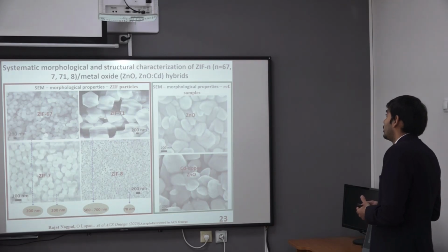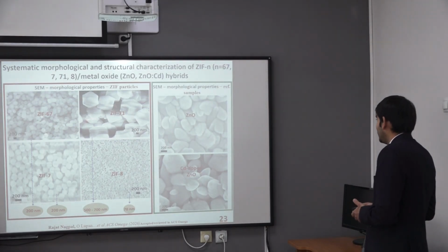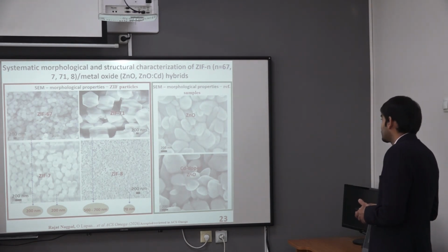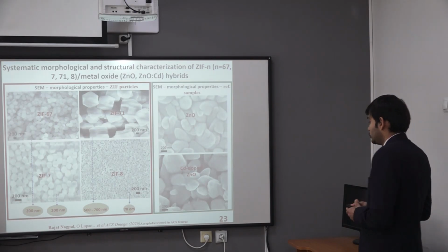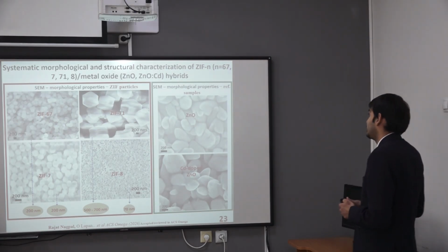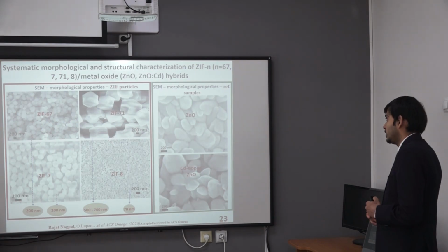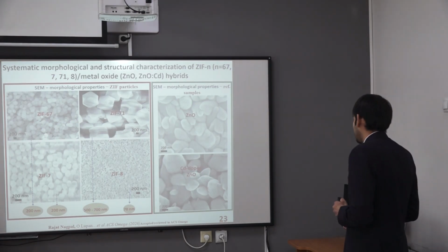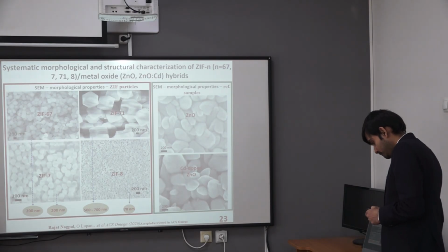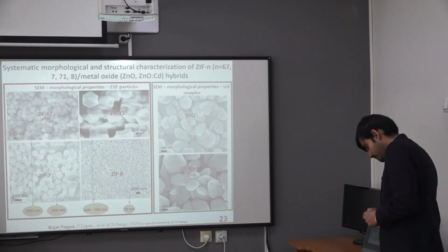But yes, in some cases, even after doing this, we observe charging effect. So one of the possibilities is using some conducting adhesion tape, or somehow making our sample more conductive, which could also reduce the charging effect. Usually one can deposit, for example, a carbon layer to do this. But it's also a good thing if you bring a conductive material close by, because there's a certain distance over which the electrons, even in insulators, cannot.